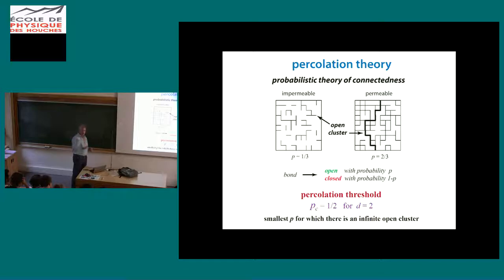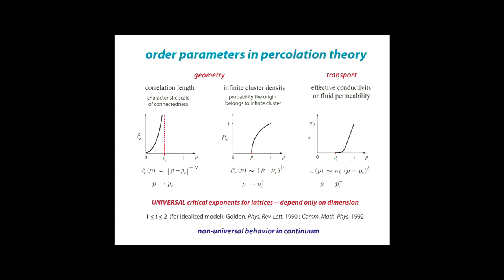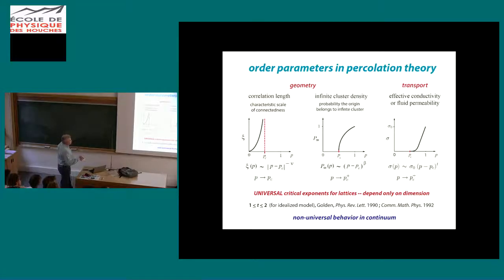There are much more interesting universal features of the system that I'll talk about. For example, the critical exponents that describe the behavior of the key parameters of the system near the threshold. The scale of connectedness, the correlation length, is known in 2 dimensions. It's 4/3, proven. Then there's the exponent that describes the takeoff of the infinite cluster density, similar to the magnetization critical exponent for an Ising model. And what we're interested in here is the effective conductivity or fluid permeability taking off above the threshold, and that has an exponent T for conductivity and E for permeability. However, for lattice problems, they're the same.